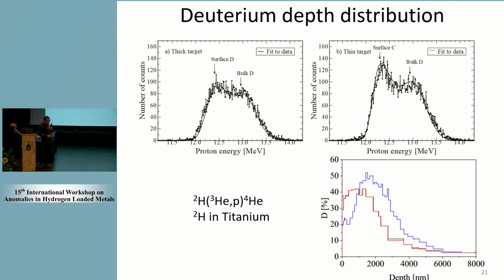And that's when we load the deuterium in the target, then we use this reaction, helium-3 on deuterium, and we measure these 12 MeV protons. If we change the beam energy, then we can get the depth profile in the target. So here is what, for example, happens in a titanium target. So this is after, I think, 1 day of loading with the ion gun at about 400 microamps at 3.5 kilovolts. And that's the blue one.